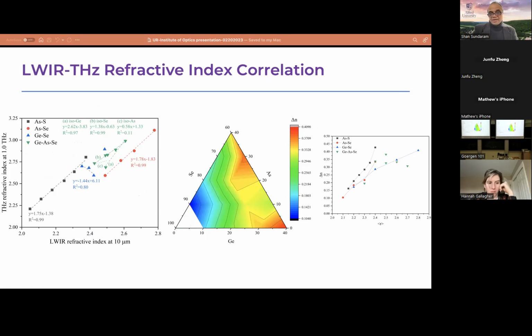So moving on to the next slide, it looks similar, but if you notice here, I'm plotting the terahertz refractive index corresponding to 1 terahertz against the long wave IR refractive index. This is more like a correlation rather than a fundamental relationship. People are interested in, if I select a family of glass, can I use it for a double purpose? Can I use them if I have the right refractive index values and absorption losses? Can I use the same glass system for long wave IR as well as terahertz?